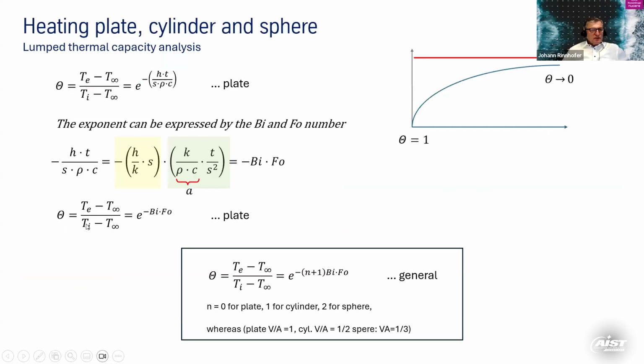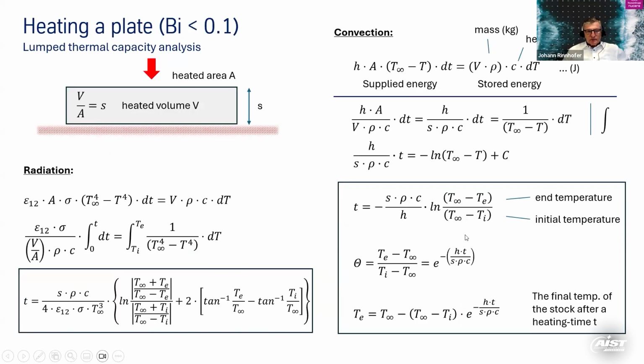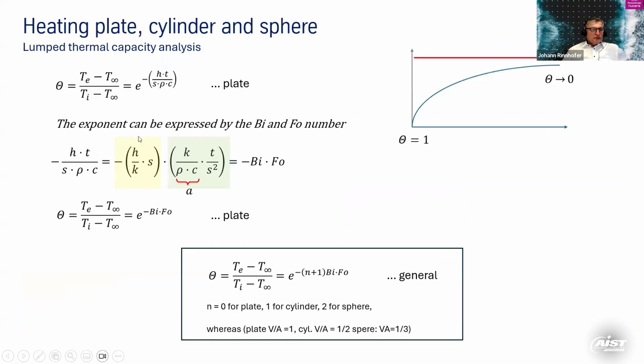When you look at this expression here, which we found in this calculation, and you modify this exponent, you extend it with K, because there's no K, no heat conductivity in there. So you add a K here, you add a K here, then you end up exactly with these expressions for the Biot and the Fourier number. That's the message. So again, you will find this expression here.